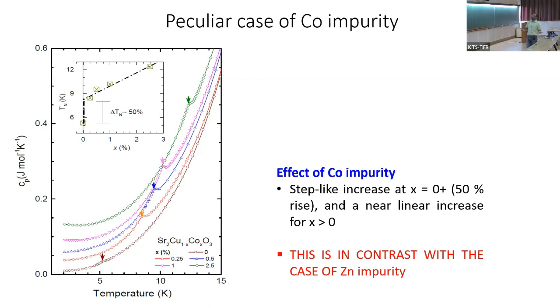Now, if you plot the ordering temperature as a function of cobalt doping, you would see that even for a very small cobalt concentration, there's a sudden jump in the ordering temperature. Now, this you cannot explain by augmentation of J prime, because you cannot say that you have put 0.25% cobalt and J prime has increased, and because of that, the ordering temperature has increased. So our hypothesis rather is that this is happening because there's a change in the universality class. So to begin with, this is a Heisenberg chain system, and cobalt is an Ising impurity, though it's spin half, it's an Ising spin 1/2. And that Isingness of the cobalt actually gets transmitted to the entire chain because of the strong p-d hybridization.